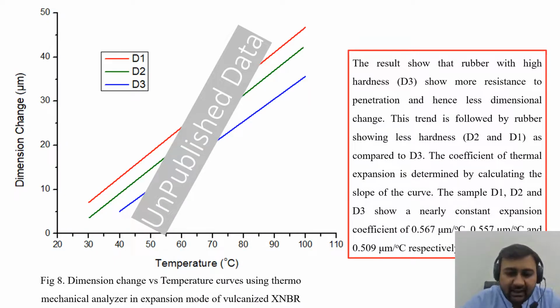So these are the dimensional change vs temperature curves obtained using the thermomechanical analyzer in the expansion mode for the vulcanized XNBR rubber. The results show that rubber with the highest hardness shows more resistance to penetration, hence less dimensional change. The trend is followed by the rubbers showing less hardness, D2 and D1, as compared to D3. The coefficient of thermal expansion is determined by calculating the slope of the curve, and the coefficient of thermal expansion is nearly constant for all the rubbers.